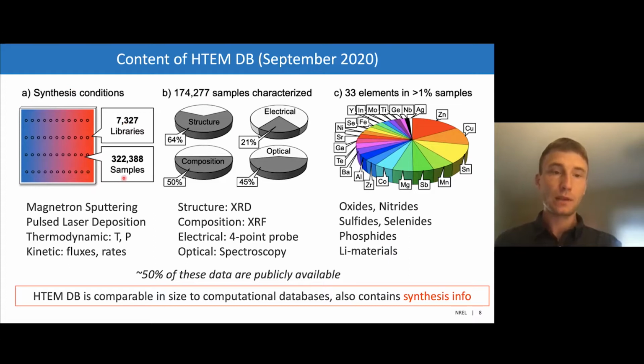We have synthesis conditions reported for most of these libraries, and they correspond to typical synthesis conditions of techniques like magnetron sputtering or pulsed laser deposition or MBE, so physical vapor deposition methods for inorganic materials. These include both thermodynamic properties, like temperatures at which these materials are grown or pressures, as well as more kinetic parameters that are often computationally difficult to capture, for example, fluxes or rates of gases or metal precursors that have been used to synthesize these compounds.